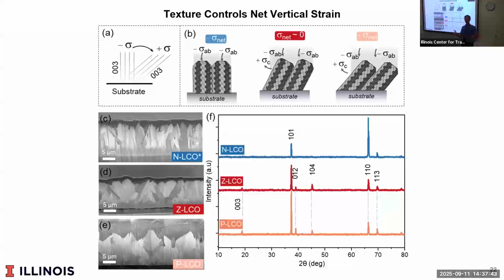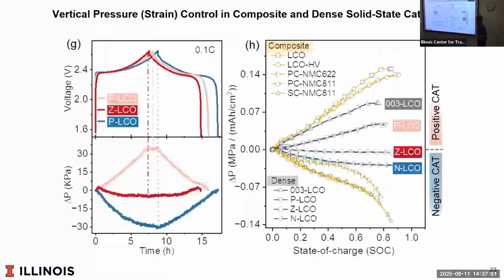Here's the same thing. We've basically created one that has no chemical expansion in the direction that matters. And so we can see when we cycle the cell, this is a lot of details here, but this is basically the change in pressure as you charge and discharge. We can orient it so that there's no change in pressure in the cell. So what this basically means is that as the cell charges and discharges, the expansion of one side exactly matches the contraction of the other, and that helps reduce cracks, defects, voids, and lots of other problems.